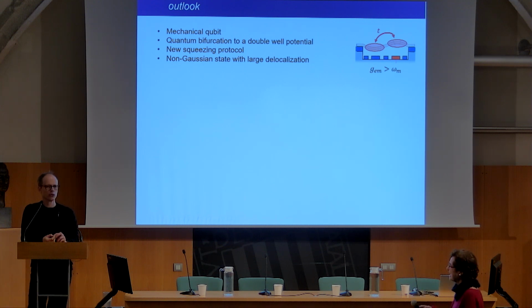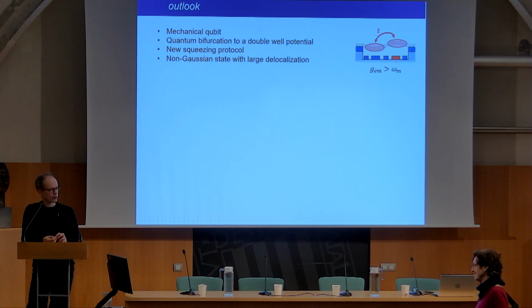So what we do is, we make many devices, and then we select devices where the resistance is below 50 kilo ohm at room temperature, because when you go to lower temperature, the resistance usually does not diverge, and this already indicates there is no missing carbon atom. Otherwise, if there was a missing carbon atom, you would have a resistance that diverges because you have a 1D system.